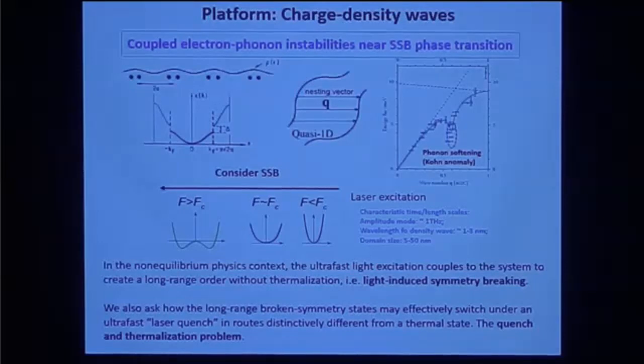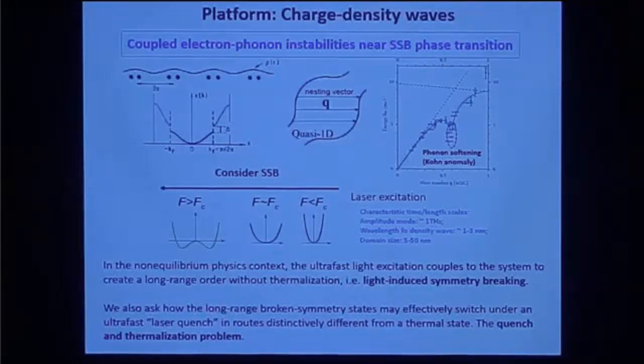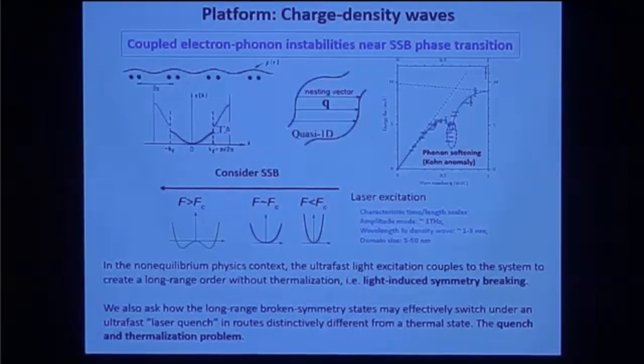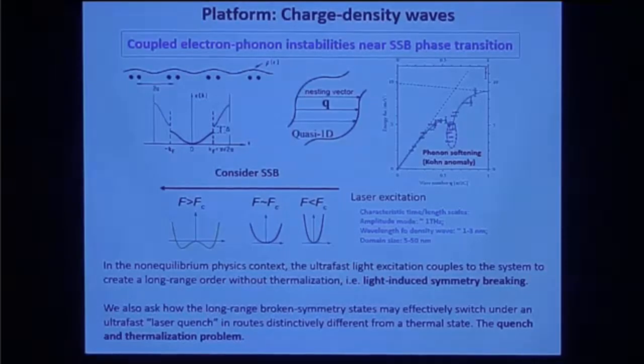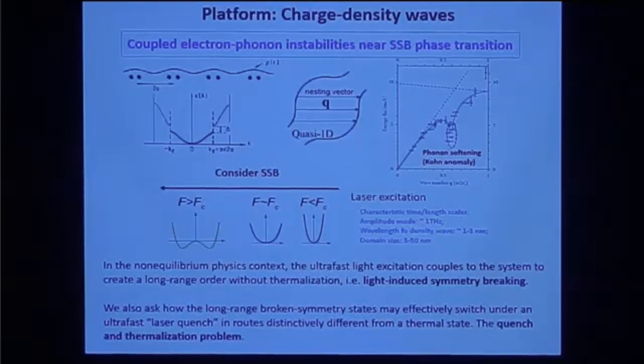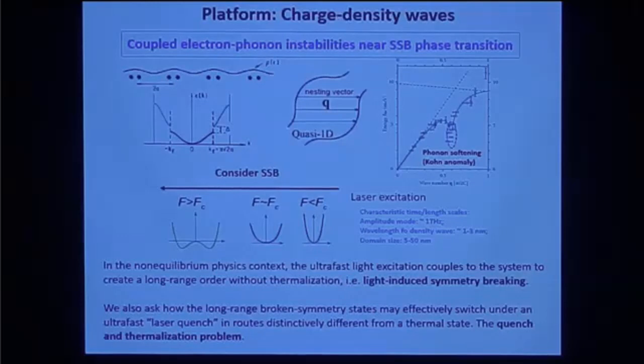Microscopically, people talk about Fermi surface susceptibility, where at a particular wave vector the susceptibility is very large and that triggers an instability, hence forming a density wave. With this system, we'd like to ask two questions using a laser. First: can you introduce a new broken-symmetry order? Typically when people talk about lasers, they talk about melting — heating the material. So-called photo-induced phase transitions involve inducing new long-range order. The second question is about thermalization: when you interact with the system via laser, the laser deposits energy and the system eventually thermalizes. These are two different questions we need to address.